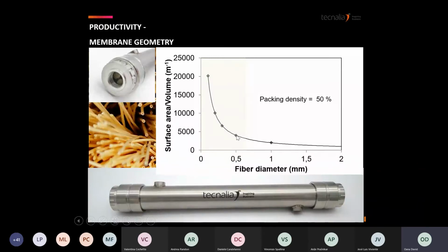Starting from an outer fiber diameter lower than 0.5 millimeters, there is an exponential increase in how much area can be packed in a unit volume. And this is why the hollow fiber geometry is preferred with respect to the planar one, which cannot be packed so densely.